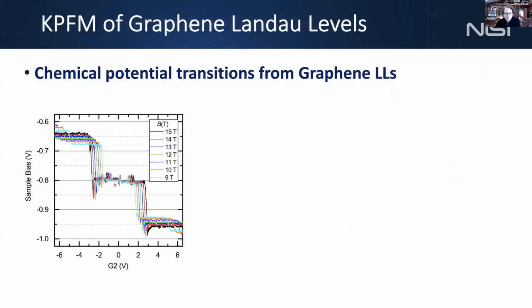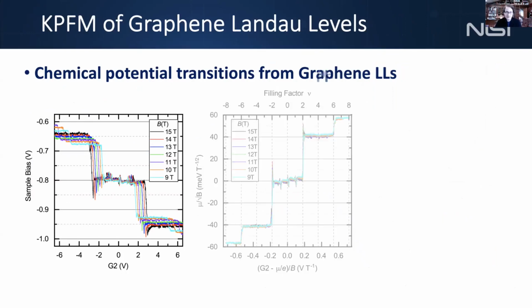And that's shown here. So I'm doing now this AC Kelvin probe measurement. You see a bunch of Landau level plateaus and transitions. We know it's graphene, so we can scale that. So we can collapse all that data onto a single curve. We scale the energy by square root of B. Remember, I told you the Landau level scale is the square root of B. We scale the density by B. And all this data collapses on the single curve. This is nothing more than the Landau level energies. So if I plot the density of states of the Landau levels, you can see there's a 1-to-1 correspondence between all the plateaus and all the Landau levels. So we have a nice new Landau level spectroscopy tool with the AFM Kelvin probe measurements.